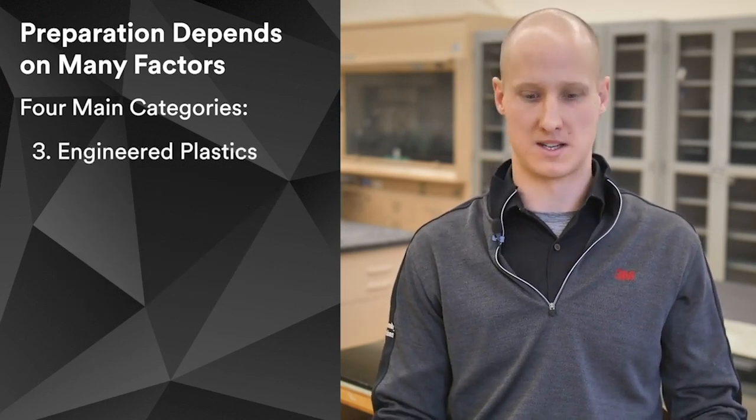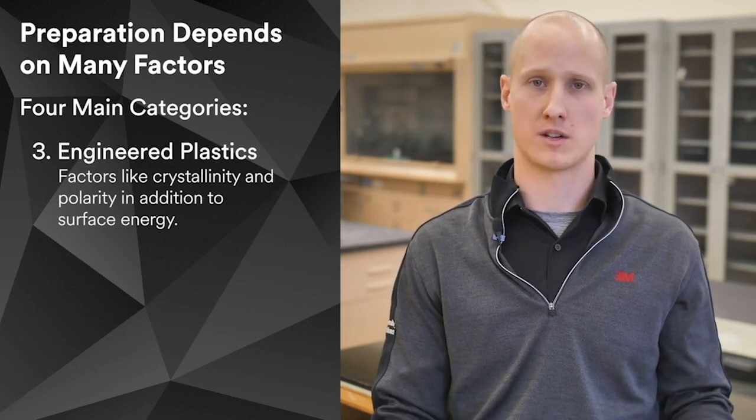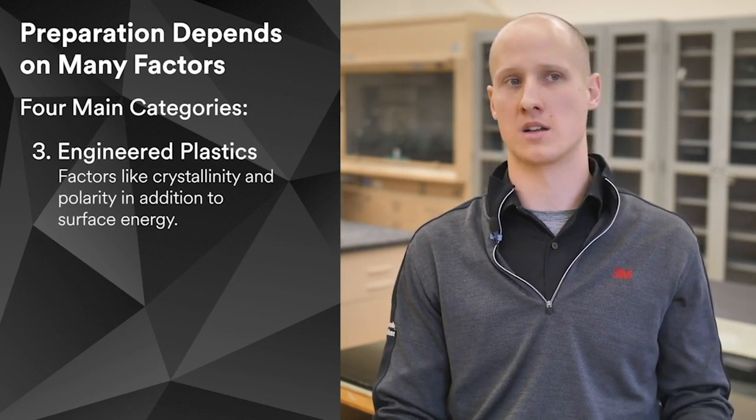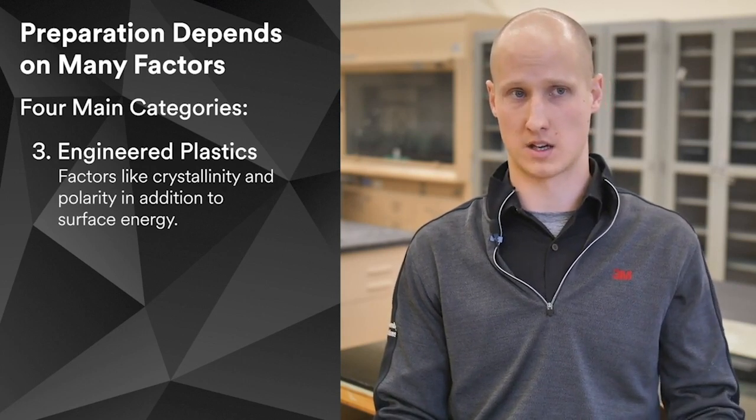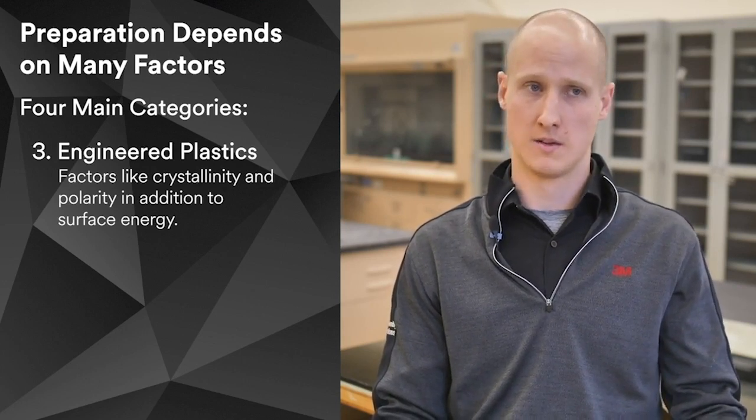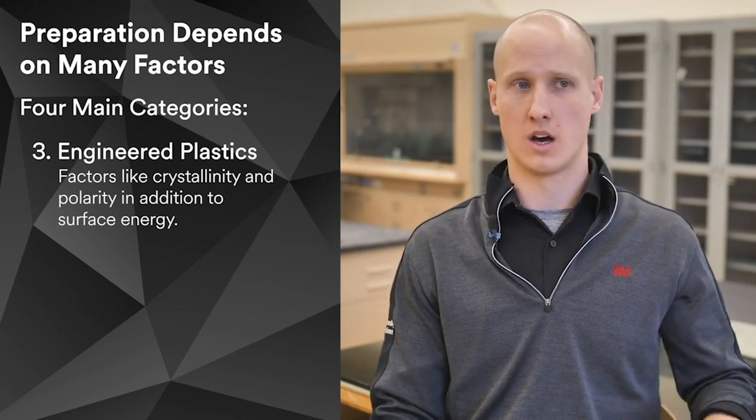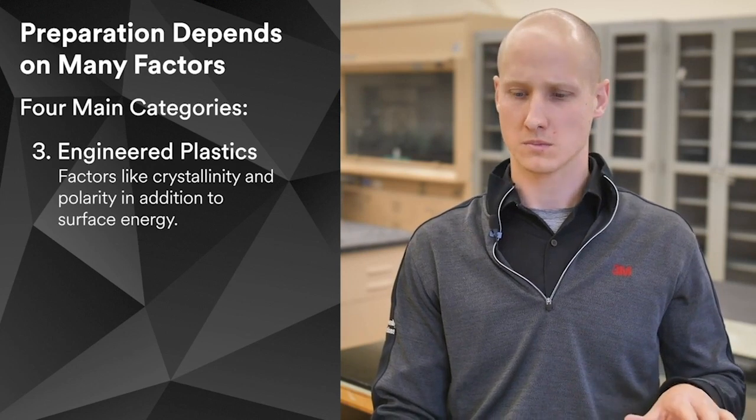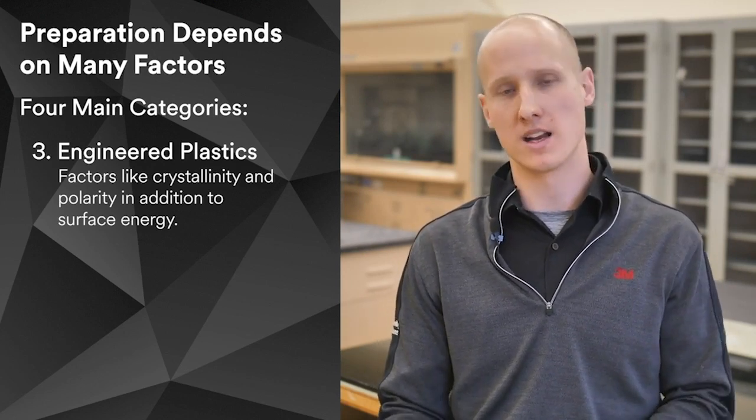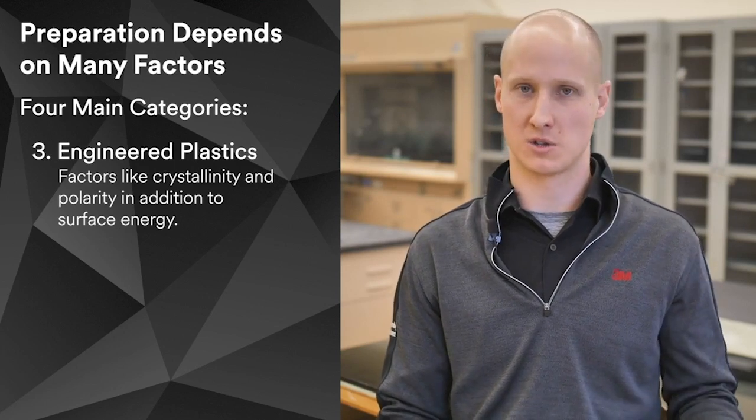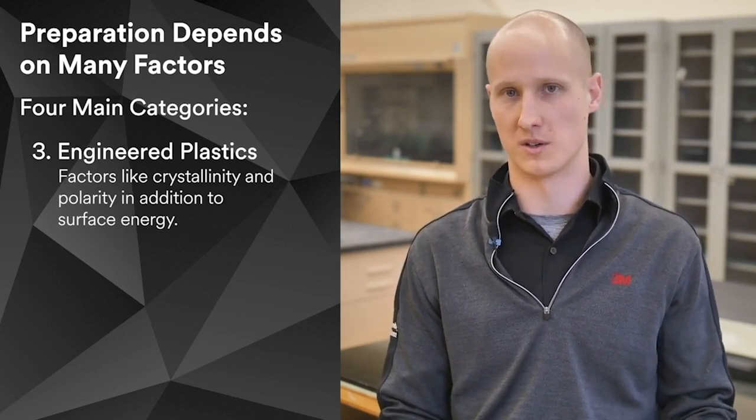Engineering plastics are really unique because it's not just about the surface energy. The adhesive may wet out across the surface, but its ability to bond will also be dictated by the crystallinity of the plastic or the polarity of the plastic. So you have a material like nylon, which is fairly high surface energy. You'll wet it out, but it's really crystalline and not that polar. So when you look at some of the mechanisms of adhesion, many of the adhesives may bond initially, but then over time you'll still see adhesive failure unless you do some more rigorous prep.